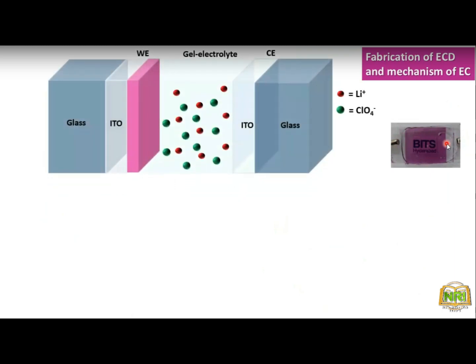So, how are we preparing it? First, we have to take this glass where ITO is coated. The ITO thickness is about 100 nanometers. We cut this ITO slide first, and on that ITO glass we deposited the film, the film we are getting on the bilayer surface. So this is one electrode, and obviously ITO is conducting, so it will act as one electrode.